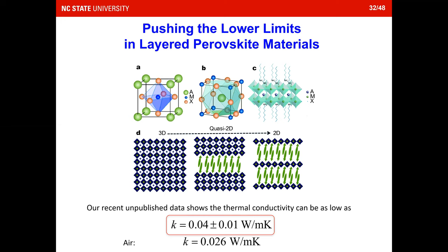So I think this can provide some promise or some hope that later on we can achieve thin film type low thermal conducting materials to realize thermal insulation. Because a lot of thermal insulation is achieved in porous materials, right? In aerogels, in porous materials, sometimes you cannot apply those locally or in very thin film forms. Hopefully by patterning this layered perovskite material, you can achieve very good thermal insulation. And those materials are very easy to make. They're a wet-based process. So it's very easy to make these materials. Hopefully we can end up with very nicely made thermal insulators.